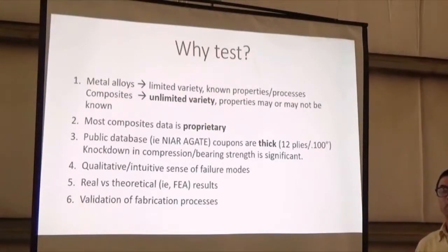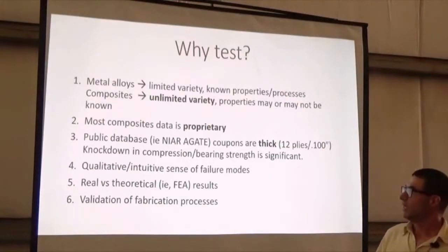So once you start doing structures that are only using a few layers of carbon or fiberglass, you get a big knockdown. And a knockdown is, they might say that a material has 100,000 pounds compression strength, but in fact, if that's a very thin material, your compression strength might be much lower. It might only be 20 or 30,000 pounds. And that's due to buckling issues and some other factors that are related to knockdown.